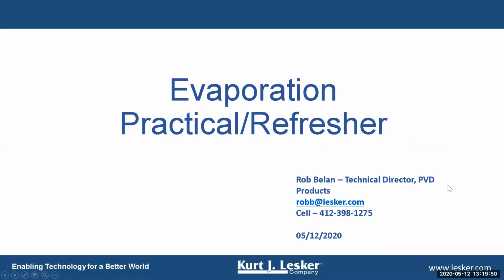Would you comment about any fundamental difference between carbon, graphite, and Fabmate? From a practical standpoint, there's not much difference. Regular carbon is a little bit cruder and more inclined to give you a little bit of dirt in the melt as you're doing the evaporation run. Pyrolytic graphite or Fabmate cleans that up a bit and reduces the amount of cross-contamination, or the amount of carbon that can get back into the melt. The idea, though, is that if you hit the crucible liner with the beam, I don't care if it's graphite, carbon, or Fabmate, if you hit the liner with the E-beam, you're going to get material into the melt.